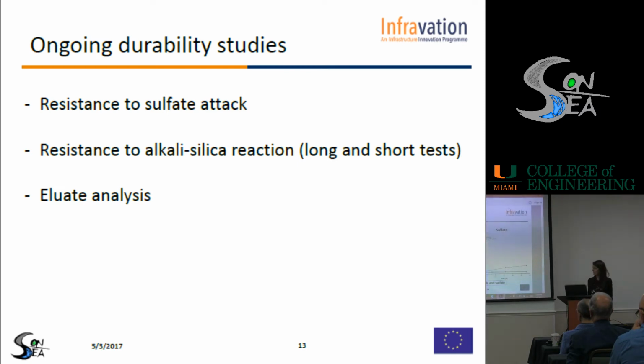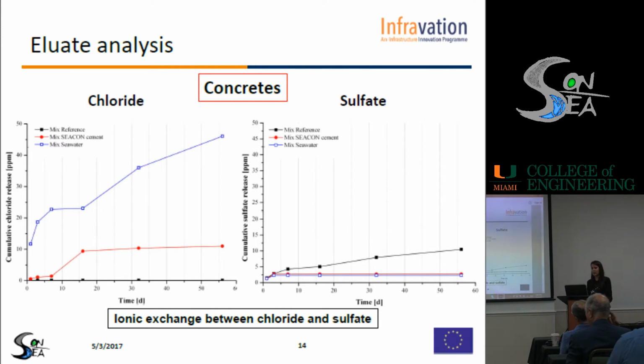So we performed this test producing the 3 concretes that I told you before. We produced cubic samples. We stored them for 28 days in a wet room, and then we submerged them in a fixed amount of deionized water. And at different times, we extracted the water, so the contact solution, and analyzed through ionic chromatography the release of chloride and sulfate in water. So from the graph, it's easy to understand that a higher chloride amount inside the concrete results in a higher release of it. In fact, the mixed seawater presents a higher release of chloride, and instead mixed reference presents a negligible release of chloride due to the negligible content of chloride.